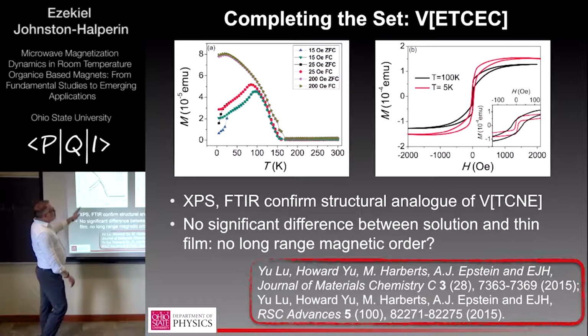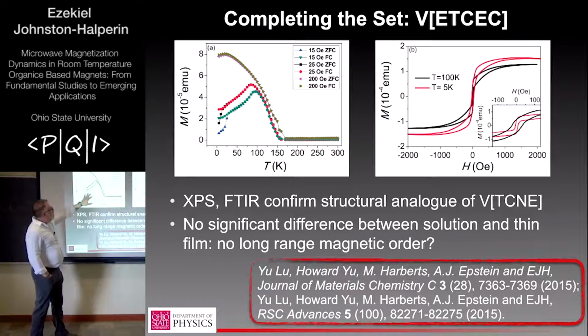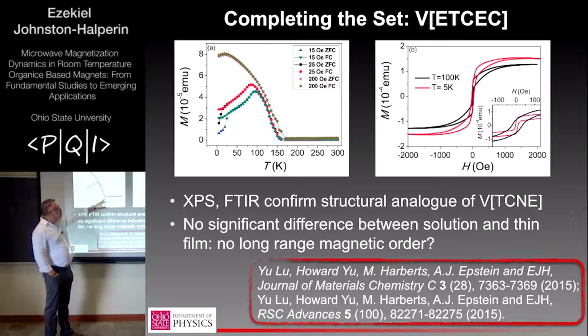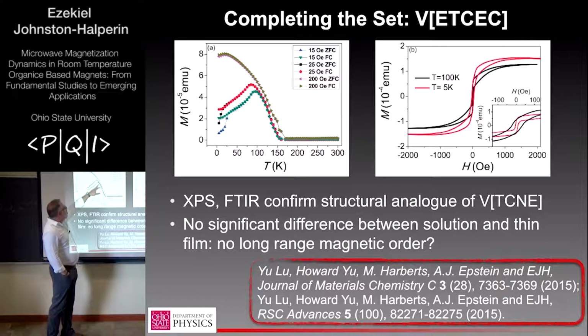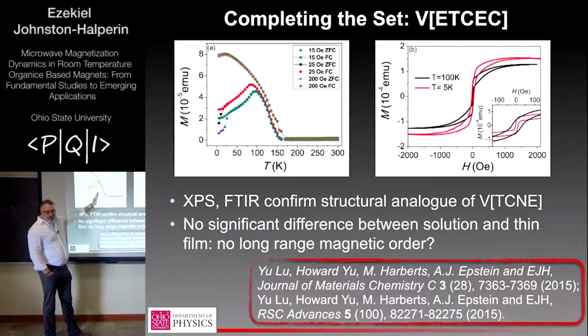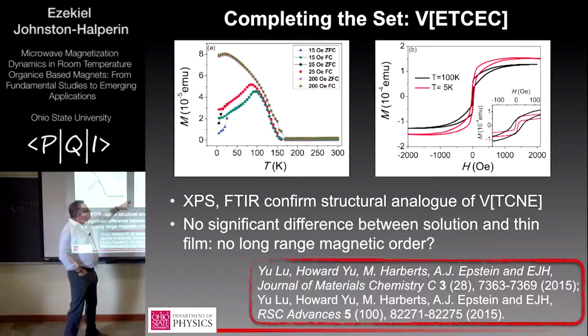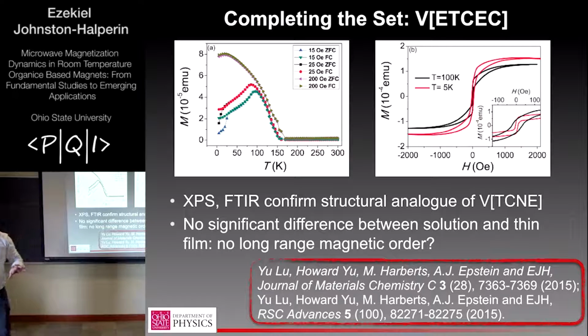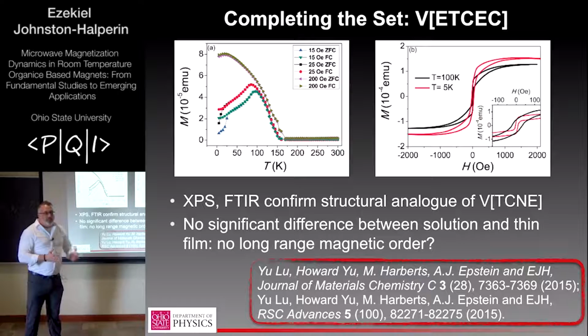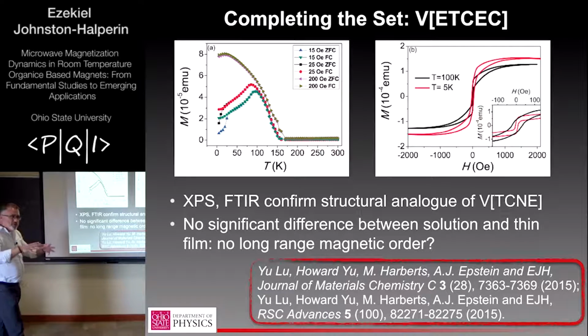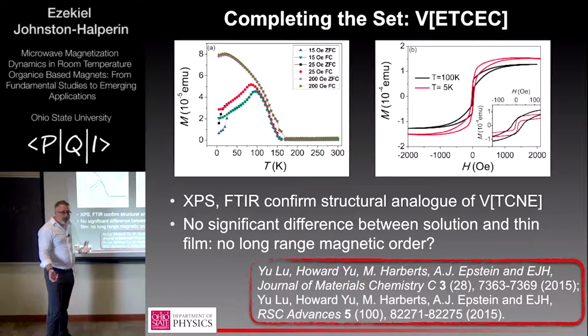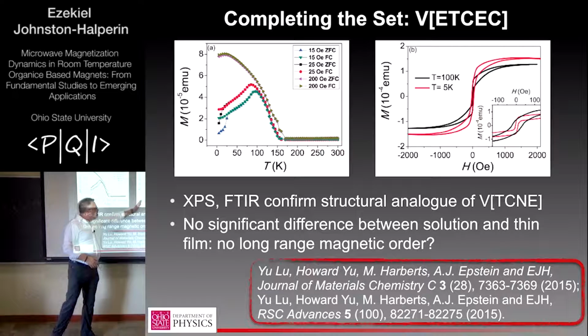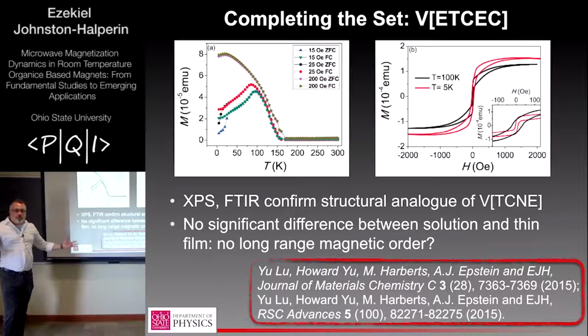And then moving even further to this ETCEC ligand, you can see the magnetic ordering now only kicks in at 150 Kelvin. Depending on the field you apply, you can anneal this out or see the same reentrant physics, which is pushed to lower temperature, because the Curie temperature has come from 600 Kelvin right down onto this low temperature transition. Moving among this set of materials, we can show, and this is some of the evidence I referred to in the beginning of the talk, that the general level of order in the film matters. Making the film more disordered and making deeper traps makes it harder to delocalize carriers. As those carriers become more and more localized, the Curie temperature becomes more and more suppressed. So we're killing the long-range order and left only with short-range order. That's one way to look at this data set.